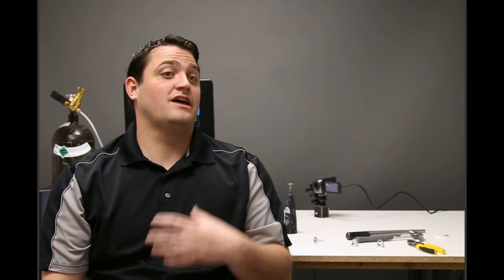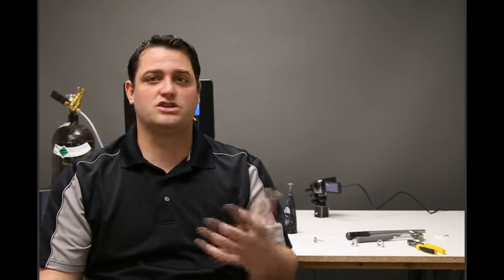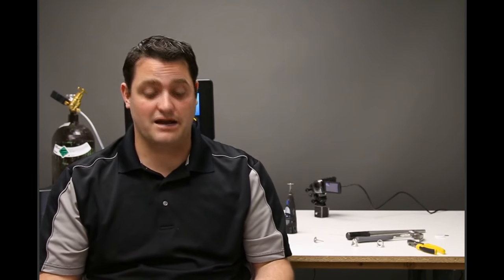Certainly we can resistance weld it with a full resistance welder, but on the Orion, it's not recommended that you try and tack that ring together with tack mode. You just aren't going to have great success with it. So just be aware that silver is not necessarily great in tack mode.